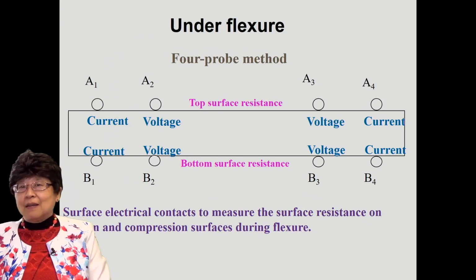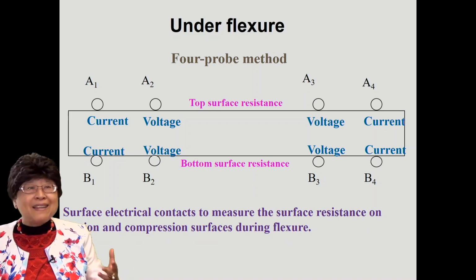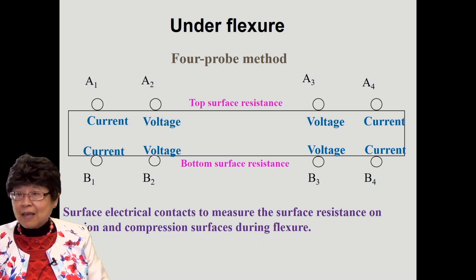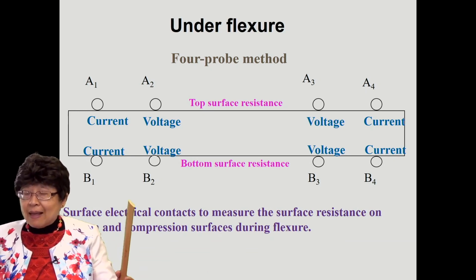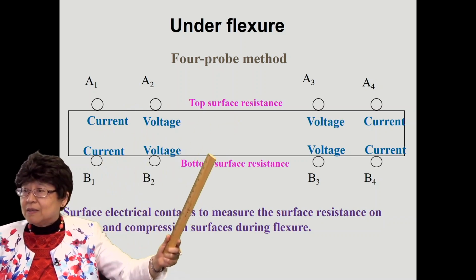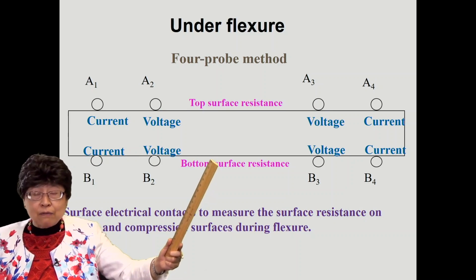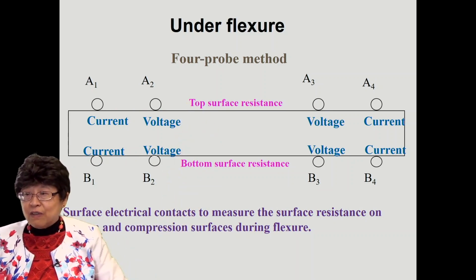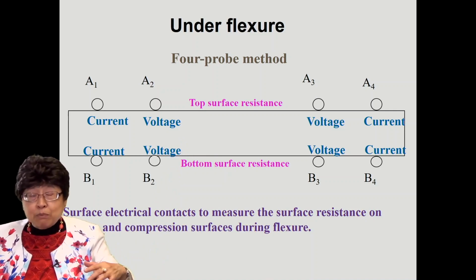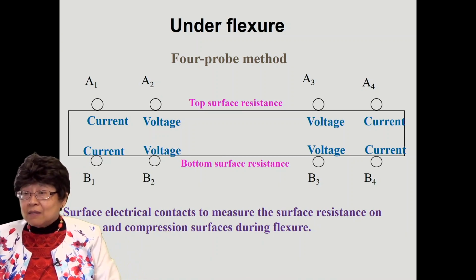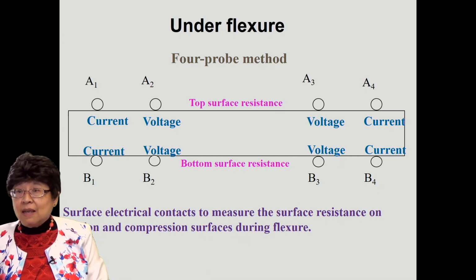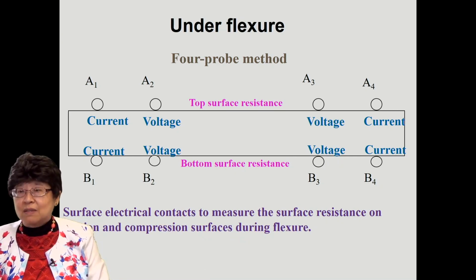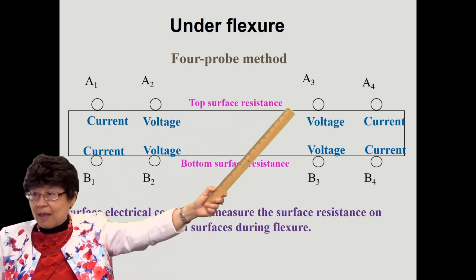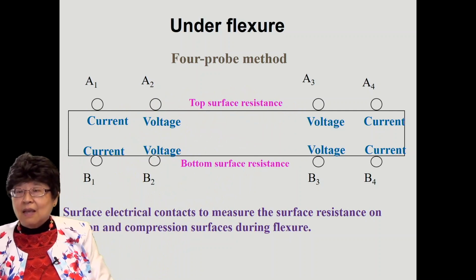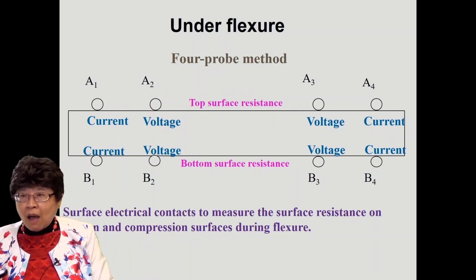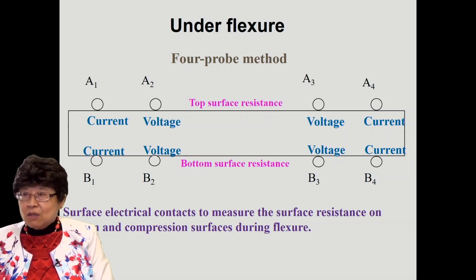Now, very often for structures, we deal with bending, beams under flexure. Under that mode of loading, the upper surface and the lower surface experience different kinds of loading. One surface is feeling horizontal tension, the other surface is feeling horizontal compression as you bend this beam. So under this situation, the way to do it is to measure not the volume resistance, but the surface resistance by using surface electrical contacts. I have 4 on each of the 2 surfaces. And in so doing, one can monitor each of the 2 surfaces in real time during the bending.